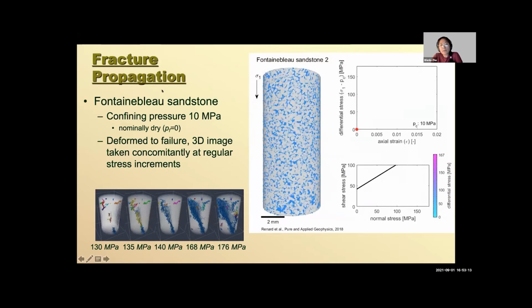One of the examples we did is, like I showed you at the beginning, in the lab we fracture rock, because fracture propagation has a lot of applications in earthquakes, in resources, in hydrofracturing and other areas. So we care about fracture growth. Now we can, for the first time, image that fracture. This is our rock: the white part is the quartz, and the blue is the pore space. Usually we color the pores blue, because that's where the pore fluids will reside. Now we did the experiments, and as it rotates, you can grab the 3D microtomography images while the sample deforms. This is what you're seeing.